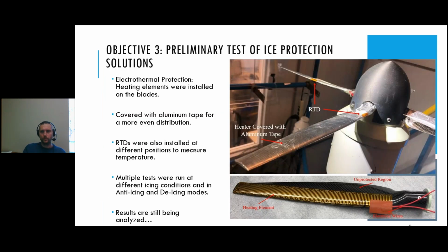Next slide, please. We also investigated the electrothermal protection. So we installed heating elements on the blades. We covered them with aluminum tape for a more even distribution of the heat on the blades. We installed RTDs at different positions to measure the temperature. And then we ran multiple tests at different icing conditions in anti-icing and de-icing mode.